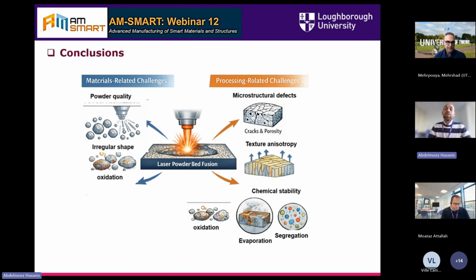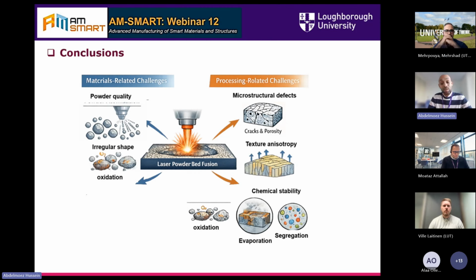From the processing, the microstructure defects, the cracking and porosity affect the magnetic properties in general, doesn't matter what it is. The texture anisotropy or the magnetic anisotropy, you can control it and sometimes you cannot, as we will see now. And evaporation, some of the elements are evaporated because they have a low melting point or low evaporation point, and the oxidation during the process itself, and segregation. All of these can affect the resultant magnetic properties.